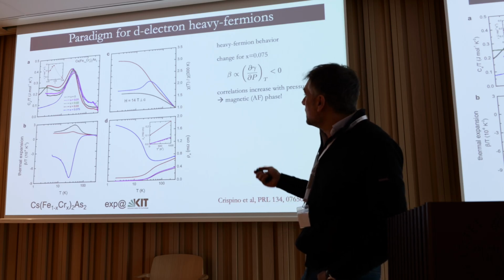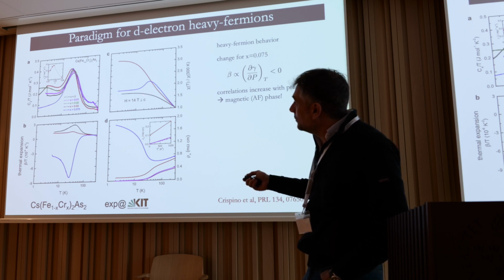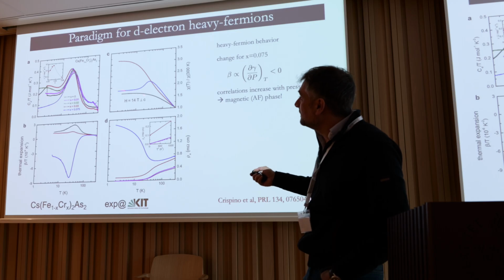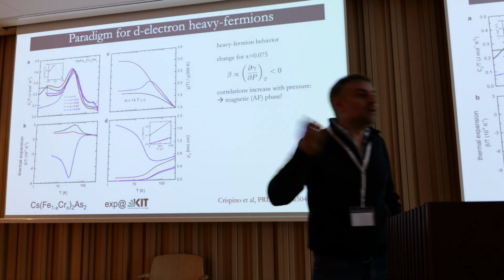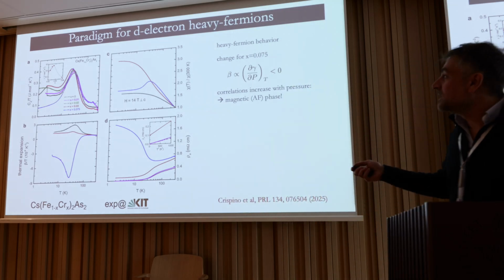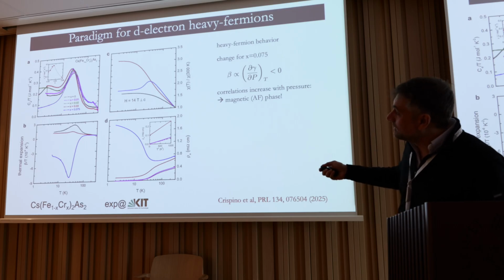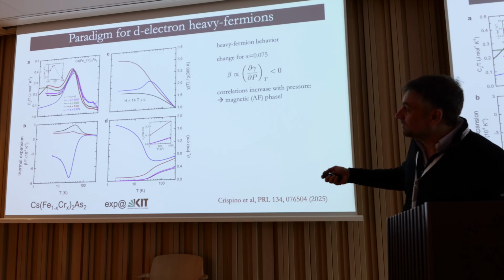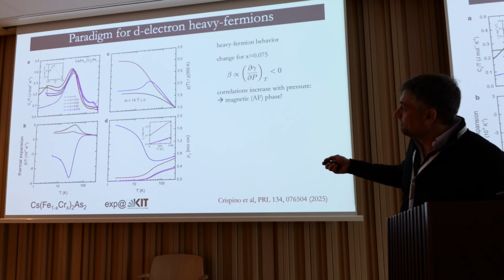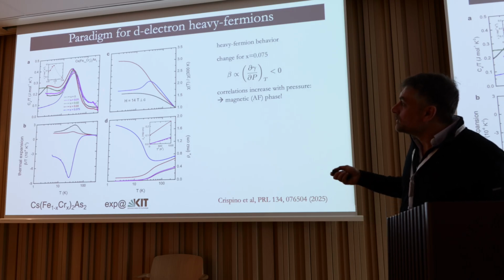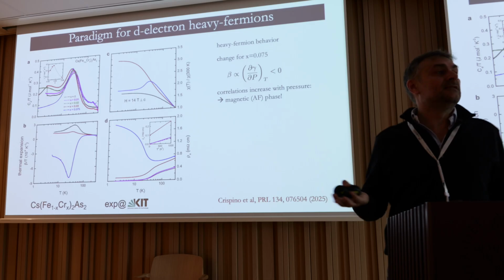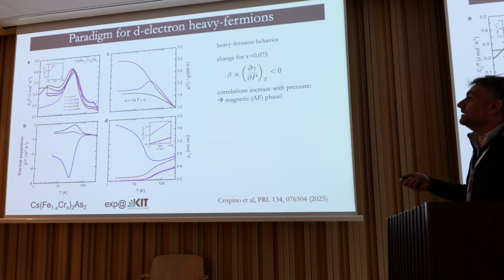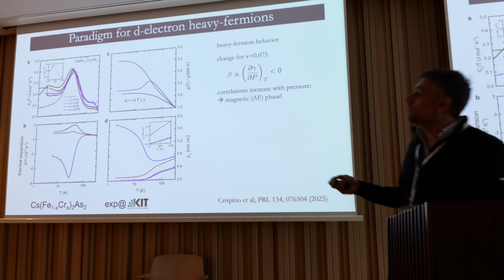If you look at the magnetic susceptibilities, same thing. Not all the compounds are represented here, but you go from the stoichiometric to the 3% and it shoots up. This is normal behavior of Pauli susceptibility of heavy fermions that we expect. And then something happens all of a sudden for this 7.5%, which looks like an antiferromagnetic transition. This is the typical shape of magnetic susceptibility of an antiferromagnetic compound.